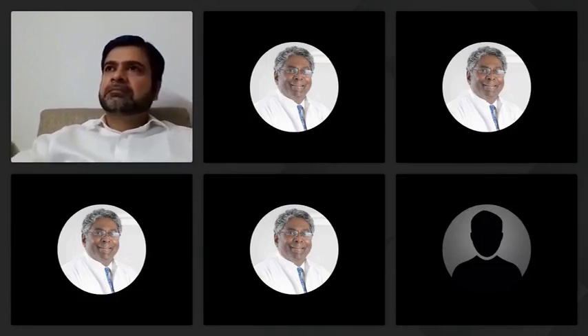The next question again goes out to you, Dr. Farooq. How much of bone to implant contact was achieved with these implants? Yeah, as I had shown in the slide, through the micro CT analysis and histomorphometric analysis, we had got a bone to implant contact of about 85.6% or 85.5% at 12-week sample, actually.